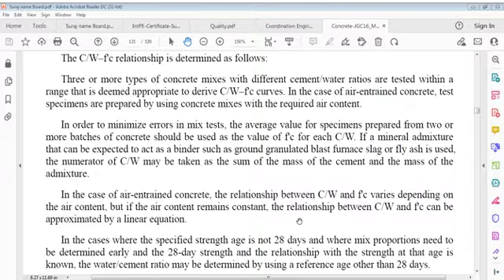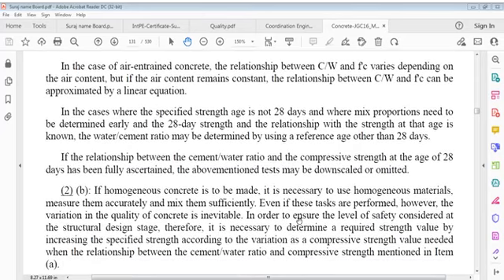In order to minimize errors in mix tests, the average value for specimens prepared from two or more batches of concrete should be used as the value of f'c for each cement water ratio. If a mineral admixture that can be expected to act as a binder, such as ground granulated blast furnace slag or fly ash, is used, the numerator of cement water ratio may be taken as the sum of mass of cement and mass of admixture. In case of air entrained concrete, the relationship between this ratio and strength varies depending on air content. If air content remains constant, the relationship between CW and f'c can be approximated by a linear equation.